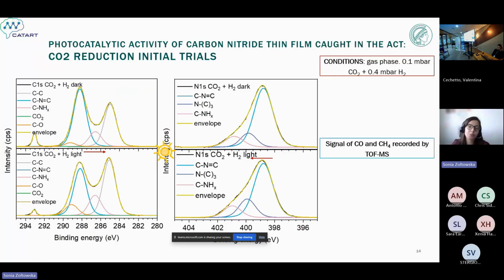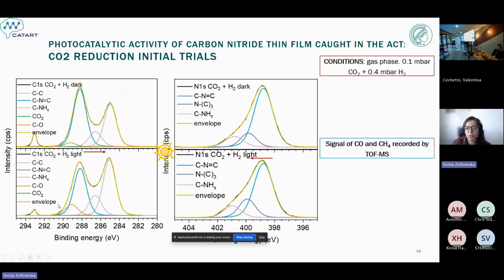But what happened when we shine the light? Then, as you can see from the bottom spectra, we observe again a shift of the carbon levels towards lower binding energies, with a decrease of the population of the feature associated with adsorbed CO2 species, and an increase in the population of the CO species. That suggests to us that indeed CO2 reduction, or some reaction of the CO2, occurs on the surface of the carbon nitride.